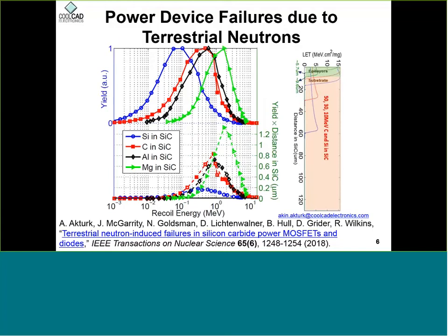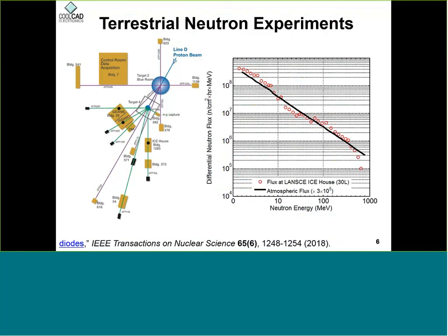The green curves show that if you have a silicon knock-on, it may travel, with I believe about 15 MeV energy, up to 6 microns within silicon carbide. And if it's a carbon knock-on, it can travel up to 10 microns within silicon carbide. But for a knock-on to cause a power device failure, it doesn't need to travel the whole length of the epi layer or the drift layer.